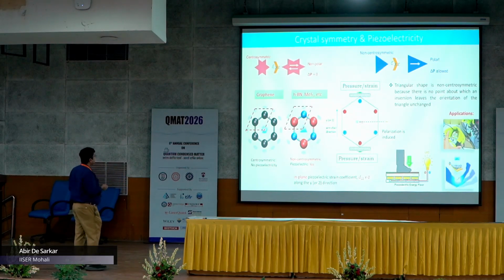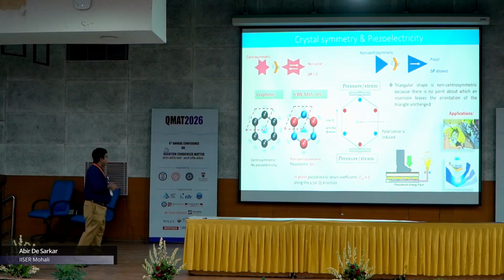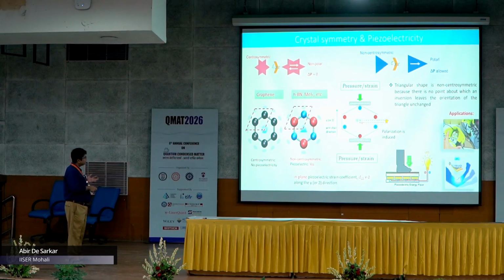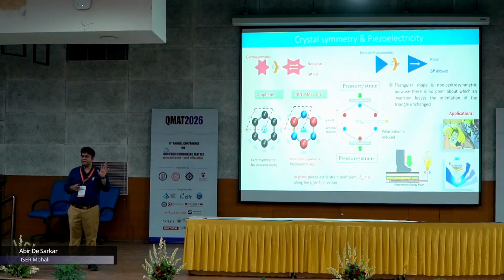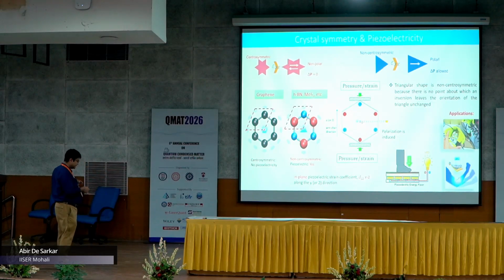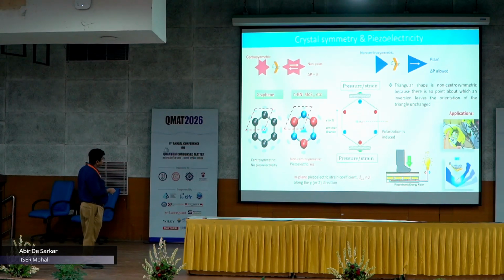And not all materials exhibit piezoelectricity. Only those materials which are non-centrosymmetric, where the inversion symmetry is broken, show piezoelectricity. Graphene, being centrosymmetric, doesn't show piezoelectricity. But these two-dimensional monolayers, where the inversion symmetry is broken, exhibit piezoelectricity.